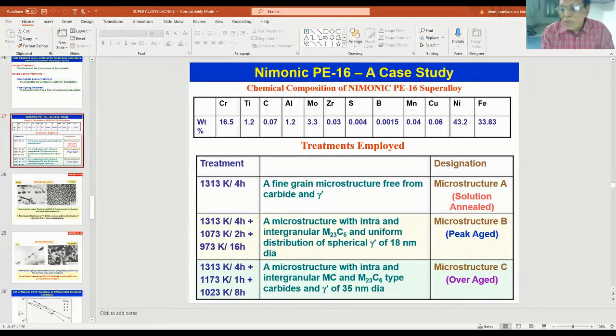Now another treatment I have given such that the microstructure will be in the overaged condition. That means gamma prime, instead of 18 nanometers at the peak condition, is now 35 nanometers, which is the overaged condition. Here you see the heat treatment that has been employed in between.